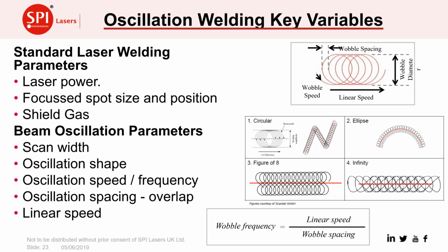So when we talk about oscillation welding, there's a number of key parameters that need to be set up, some of which are independent, some of which we can link together. From the laser side, we've got the laser power, the spot size and the position. Those come from the way we set up our optics, and then we have the decision on whether to use a shield gas or not.